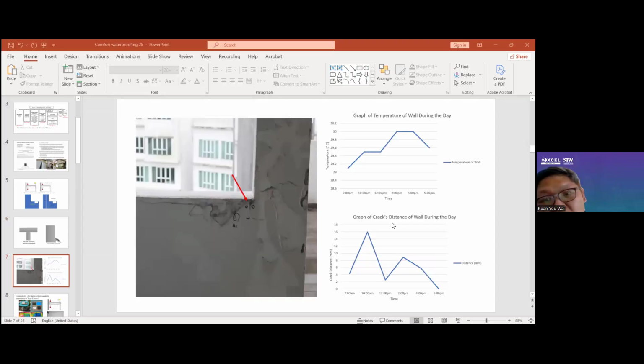So I would like to illustrate with some of the studies that I've done on my own. This is actually a wall below the flat roof, and this wall has a crack. I punched two holes in this wall, and I measured the temperature of the wall as well as the distance between these two holes. I discovered that according to temperature change, the width of the crack actually changed accordingly. So this is significant evidence to show that the crack is actually induced by temperature change, and the change in the width can be up to 16 mm.